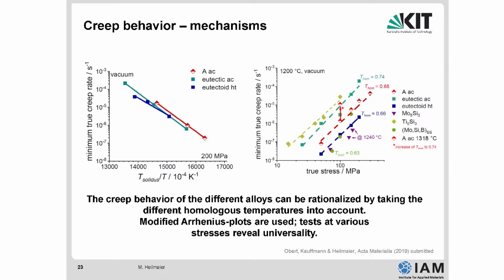So first of all, the new alloy A, as you can see, which is still oxidation resistant but contains eutectoid regions, shows a better creep performance than the eutectic alloy. The reason why this is the case is very simple, because the melting points of all these alloys are different. The melting point of the eutectic alloy is lower than the melting point of the eutectoid alloy. And when I say melting point, I mean the point where the first phase starts to melt.